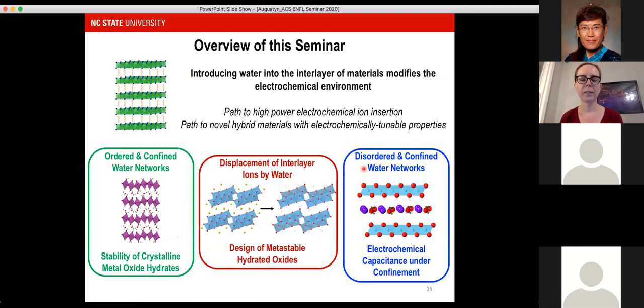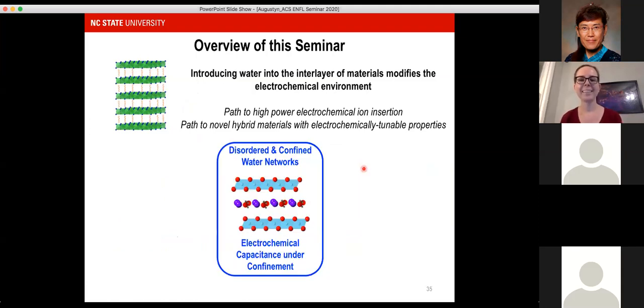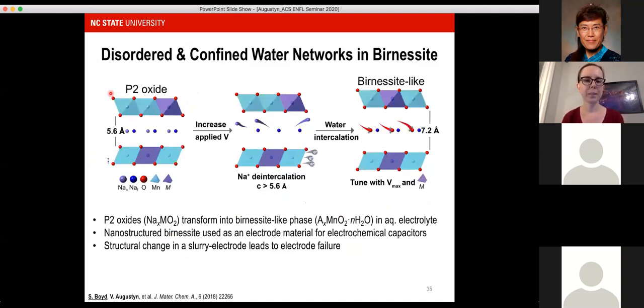So now I'll talk about the last part of the presentation, where we take this disappointing result, if you will, of electrodes failing, and observe something very interesting that tells us about electrochemical capacitance under confinement. So I just showed you the story. We take the P2 oxides, we remove sodium from the material by applying potential. At some critical desodiation level, water comes in from the electrolyte, we believe, to offset the repulsion between these layers, and you get this birnessite-like phase. Birnessite is a well-known material in the electrochemical capacitor community, but when this process occurs on the electrode, this volume change results in electrode failure.